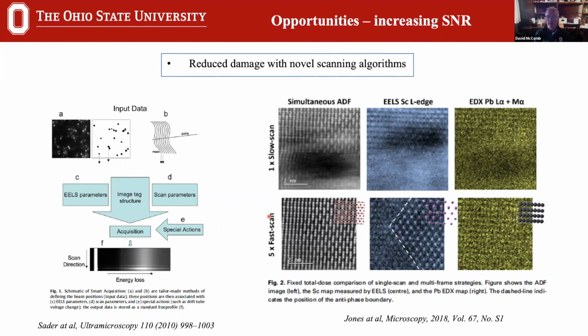And one mechanism to do that that we're exploring is actually using novel scanning algorithms. In particular, on the right-hand side here, we see the work of Lewis Jones at Trinity College Dublin showing the effect of, for example, doing a slow scan EELS map. And you can see in this system the damage that's actually occurring in front of the electron beam, really. Again, it's this delocalization of damage and whatever that's happening. And you see this damage that occurs when we do this slow scan.